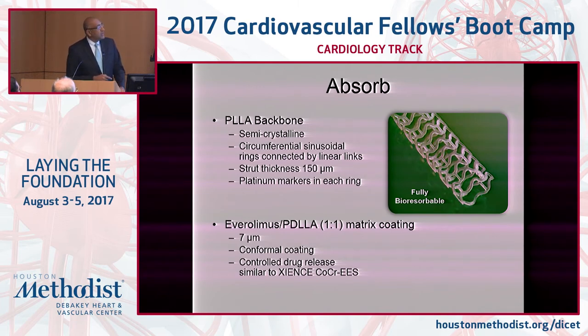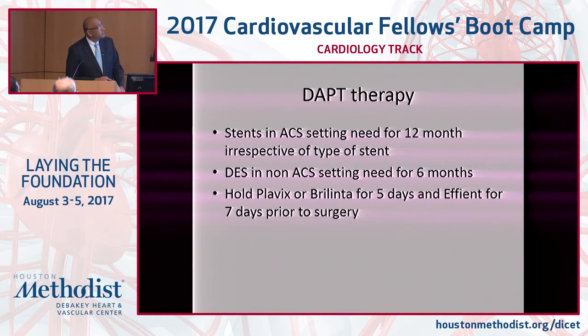But as of right now, we have found that this bioabsorbable scaffold, which dissolves at about 2 years, which sounds theoretically such a great idea, in the initial studies has really not panned out. One of the biggest challenges is stent thrombosis. The stent thrombosis rate is about 1.5%. So remember, what did I say about stent thrombosis? 0.6% or less. So that is unacceptable, and because of that, it has not become the standard of care.